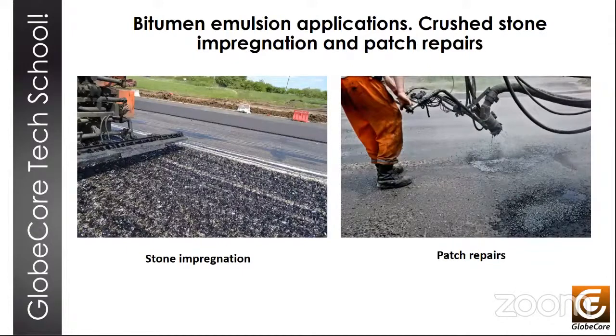Crushed stone impregnation is another use: construction of structural layers, bases, and coatings by multiple scattering of crushed stone of various fractions, compaction of such stone, and impregnation with bitumen, usually twice, with a slow breaking emulsion that contains 50 to 65% bitumen.